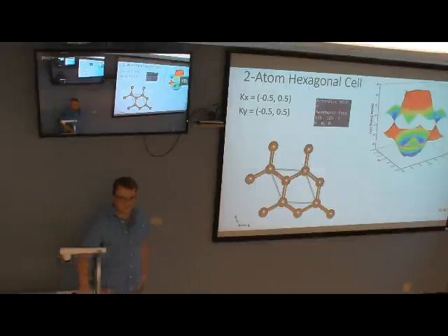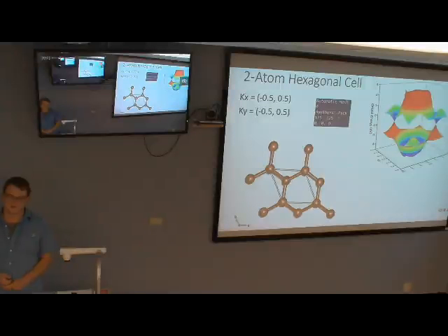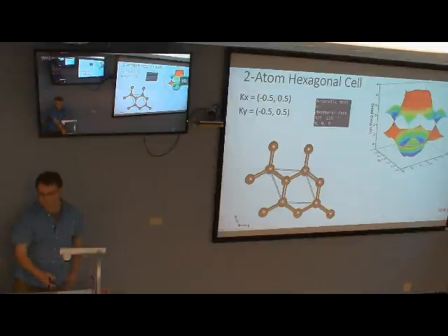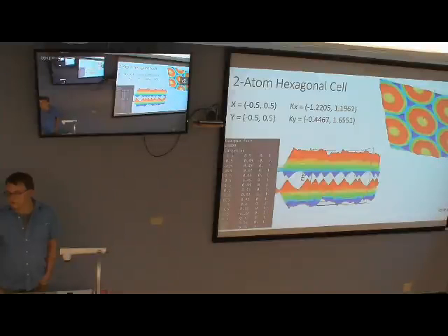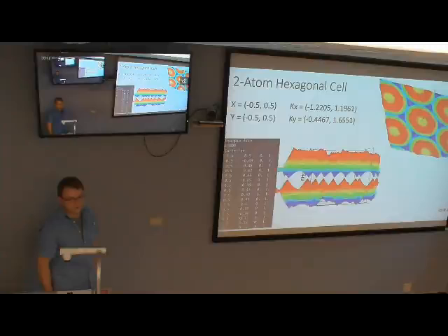So, if I migrate to a hexagonal unit cell and go back to the two-atom basis that produces the smallest primitive cell, and I use VASP's automatic mesh again, it produces for me this dispersion curve for the HOMO and LUMO orbitals, or bands. Now again, if I want a bigger picture, just for visual purposes, I can specify the k-points myself, and I do in fact see some sort of hexagonal Dirac structure.